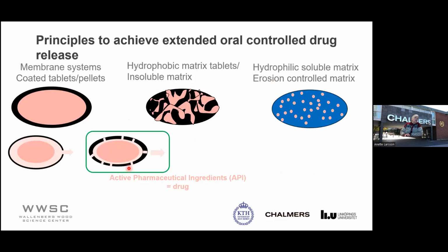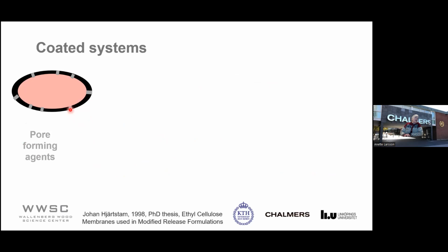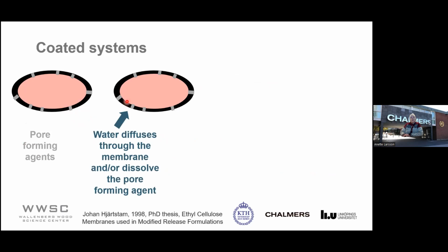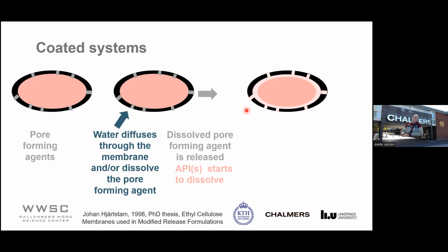Now I will go over to the other one that I have been working more with, and that is this system where you instead have pore-forming agents here in the membrane. So when you take this formulation and place it in water, the water starts to diffuse through the membrane, but also to dissolve the pore-forming agents here. And the pore-forming agent starts to dissolve and is released. And at the same time, you get water in here, and that starts to dissolve the API, and you will get pores here, or water-filled channels, where before we had the pore-forming agent here. So then through these pores, the drug will be released. And here, it is mainly the difference in concentration inside and outside the drug that is controlling the release rate.